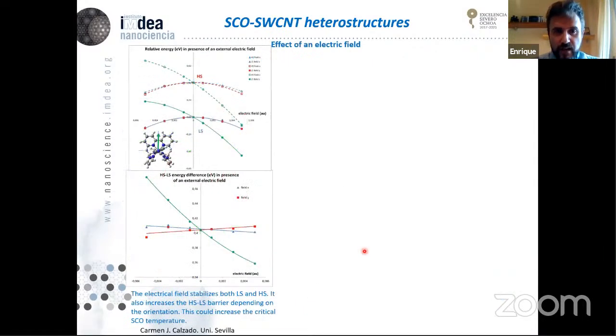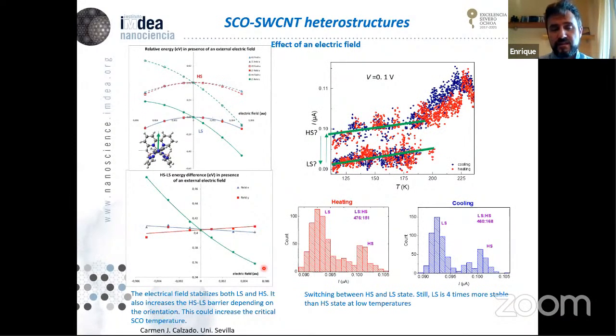Okay. Our system is also subject to a strong electrical field, so they have also tried to see what happens to the high spin and low spin state when you apply an electrical field. And it's not simple because it depends on the orientation of the electrical field, but just to show you that we could further stabilize or destabilize the high spin to low spin transition. We didn't do many measurements as a function of the bias, but we do have some at lower bias, where we have this kind of situation now.